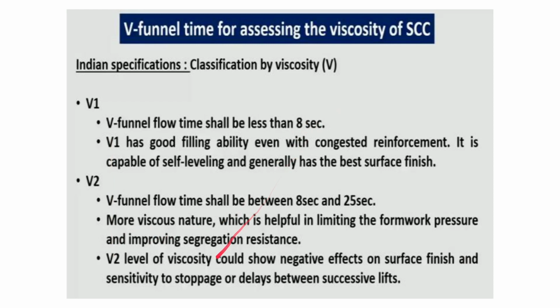That is if the V funnel flow time is less than 8 seconds. But if the V funnel flow time is between 8 seconds and 25 seconds, then it is categorized as V2. This is more viscous in nature, which is helpful in limiting the formwork pressure and improving segregation resistance, because the viscosity is relatively higher. But the V2 level of viscosity can also show negative effects on surface finish and sensitivity to stoppage or delays between successive lifts. So it has both pros and cons, and we have to see which we require.